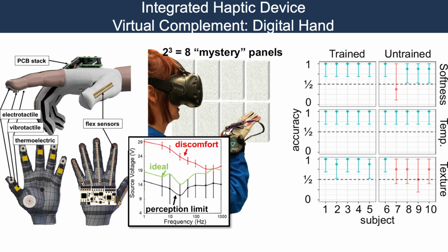But what I really want to highlight here is how this combination of actuators allows you to differentiate the material properties of what we called mystery panels in a VR experiment. We had two cohorts of participants, one in which the participants were trained, so that is, we applied the stimulus and we told them what it was. So we applied an intermittent electrotactile signal for rough, and then we applied a constant electrotactile stimulus for smooth, which was just kind of a low hum, and then temperature, hot, cold, and then softness was judged by the frequency of the vibrotactile effect. So a high frequency for a hard tap against the surface, and low frequency for a softer material under the same tap.